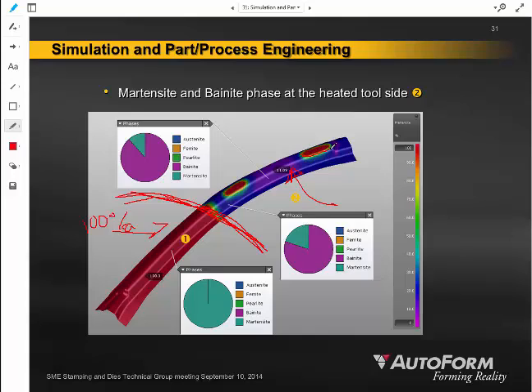But you'll also notice a manufacturing-induced difference that we recognize, that perhaps in these two areas I just circled, those two areas were areas that had early contact with the die during the forming operation. Those were, in fact, in this simulation that I ran, I had spring-loaded pads to support the blank prior to closing the tool in this operation.